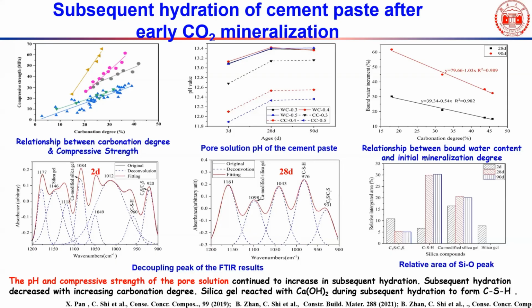On the other hand, after carbon mineralization, initially we can find silica gel form, but as we immerse the specimen in water, later on the silica gel will disappear. That's because the cement hydration will release calcium hydroxide, right? Calcium hydroxide will react with silica gel to form calcium silicate hydrate. So this will be similar to conventional Portland cement.